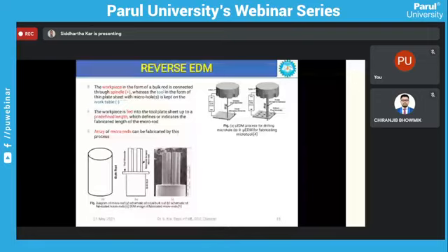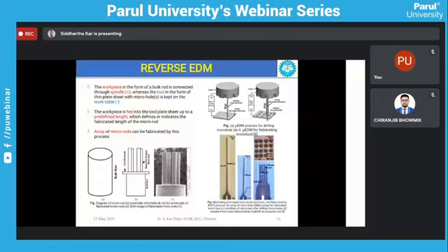So here we see that an array of 4 micro rods has been fabricated with the help of the reverse EDM process. And here also we see that a rod of 3.4 mm length and 55 micrometer average diameter has been fabricated, and an array of rods has been fabricated by drilling holes with the initially fabricated rods.